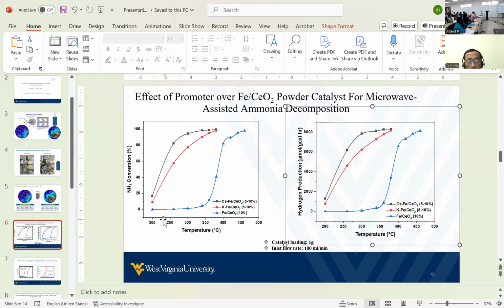So if you look at the iron-based catalyst, you heat up the catalyst only until 350 degrees C, the reaction starts taking place. Even though the reaction starts, it can struggle until they probably reach 450 to 500 degrees C. The last data point is not 100% conversion yet. It has to keep on going until 500 degrees C to reach 100% conversion. But our goal is not to hang up with this iron catalyst, because our goal is to see which promoter